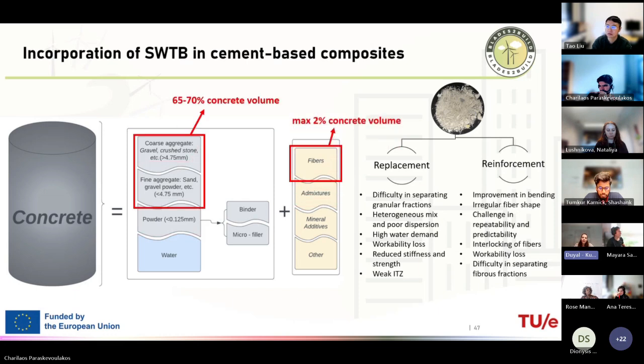On the other hand, I would like to discuss the sustainability aspect. If you would like to use this waste material in concrete, we also have to consider the amount that we can put into the concrete. Usually the aggregates are the larger fractions inside of the concrete, taking approximately 65 to 70% of the total concrete volume. However, fiber reinforcement is usually limited to a maximum of 2% of concrete volume. Even in some countries, it's even lower. So focusing on the replacement concept, and in particular aggregate replacement, can allow us to put higher dosages of wind blade waste. But how?